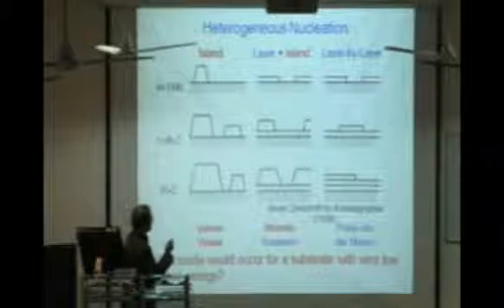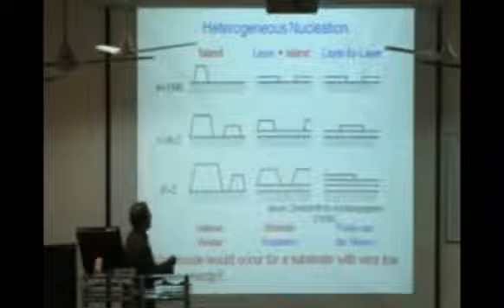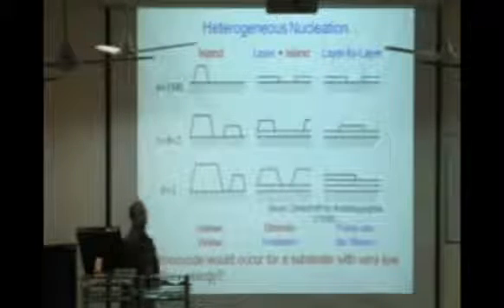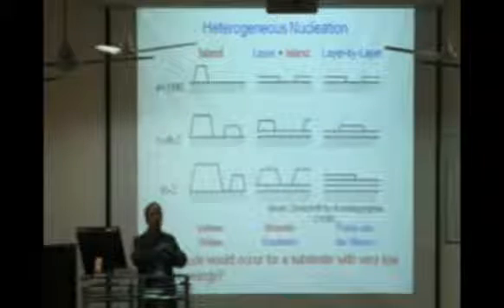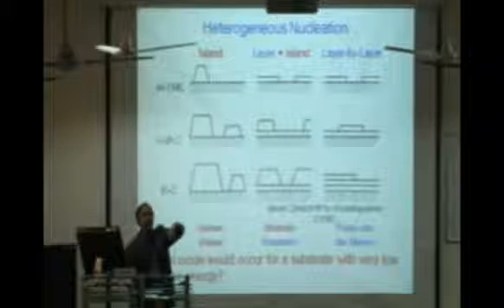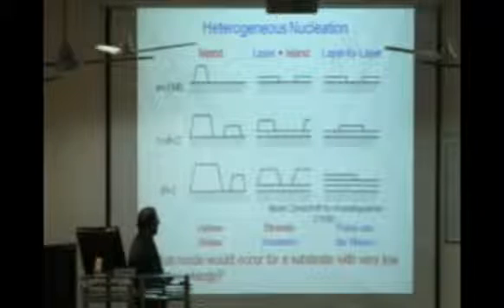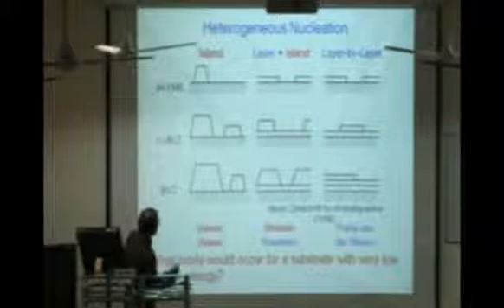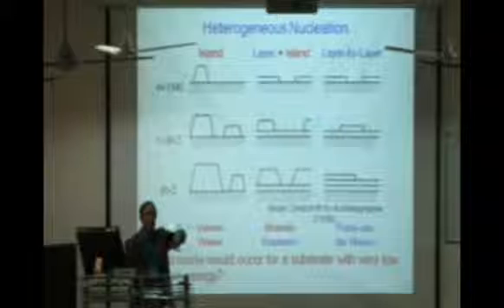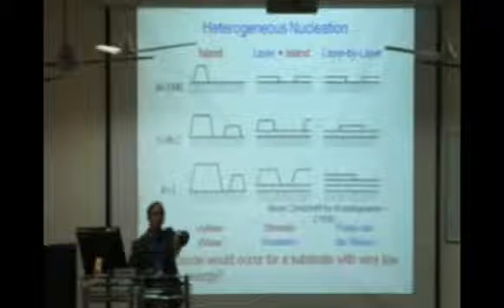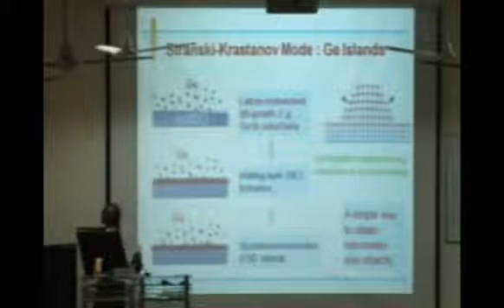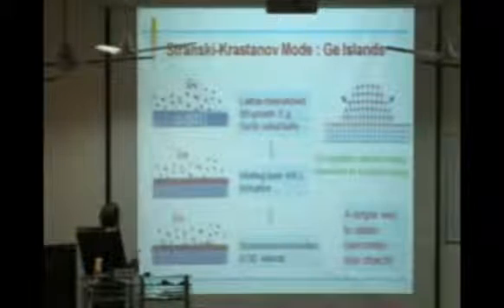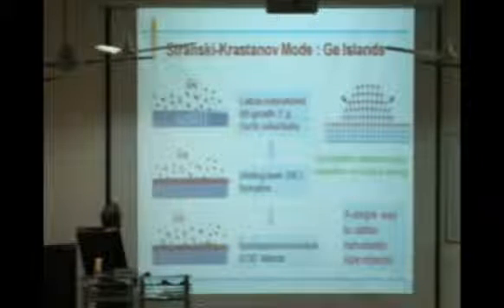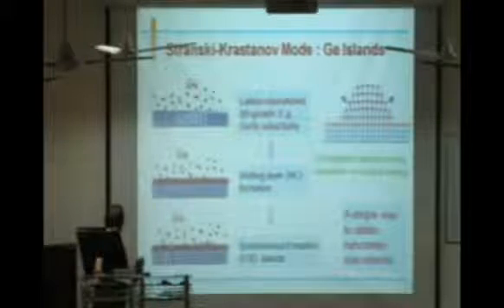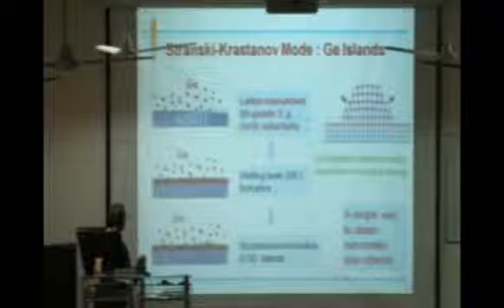If you grow a lattice mismatched semiconductor as a thin film layer on a substrate, initially it actually spreads. But since there is lattice mismatch, strain builds up, and this strain changes the growth mode from two dimensions to three dimensions. So they make so-called quantum dots. I have shown almost the same thing here. In this case we have taken a system of germanium on silicon. There are many other systems like indium arsenide and gallium arsenide. If you put germanium on silicon, initially it will spread in two dimensions.